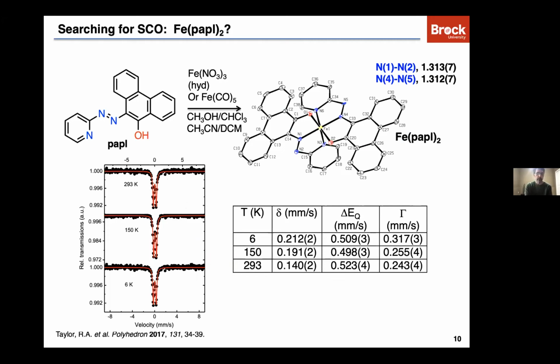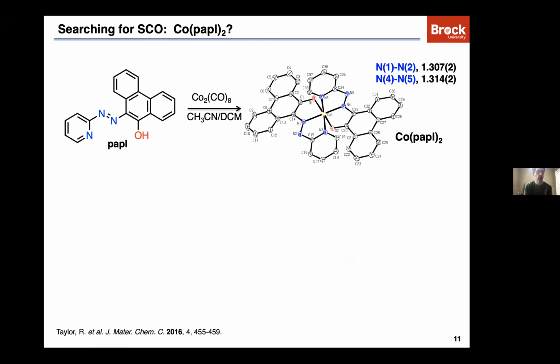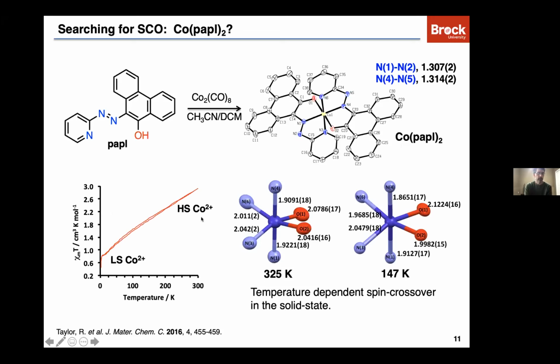Now, what about other metals? Well, what about cobalt? If you take PAPL and coordinate it to dicobalt octacarbonyl, you can generate a cobalt-2 complex, again with PAPL anions. And in this case, we do see a spin crossover, and we can track that using magnetic susceptibility measurements, and also by X-ray. At two different temperatures, you can see the differences in the coordinate bond distances. The longer bond distances are typically in the high temperature form, and you see the Jahn-Teller axis in the low spin cobalt-2 state. So we have established that we can see spin crossover in the system with these aryl azo ligands.